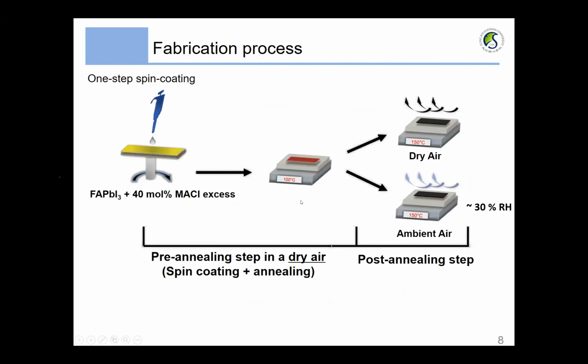So in order to investigate the humidity effect on the MACl additives during the annealing process, we designed the fabrication process like this. The fabrication process is divided into two large steps, the pre-annealing step and the post-annealing step. We varied the humidity levels for the post-annealing step. And as you can see here, the dry air and the ambient air, which is said to be 30% humidity.